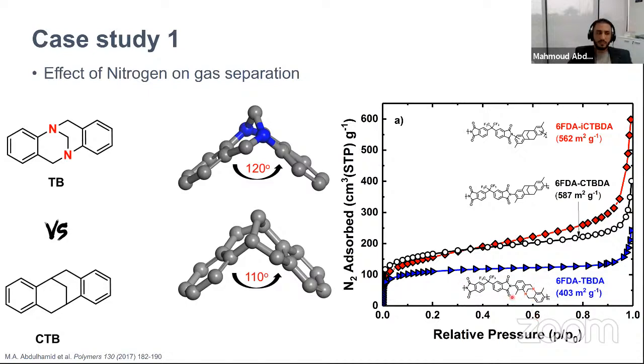So now, back to the previous slide, is this change going to be because of diffusivity or because of solubility? We did another study and found that there is no interaction happening between nitrogen and carbon dioxide, but there are interactions going on between the nitrogen atoms inside the polymer chains. So when we have a nitrogen here and a nitrogen from the other side, they interact and bring the chains together, and they have tighter porosity and tighter pore size distribution, and thus lower BET surface area, lower permeability, but higher selectivity.